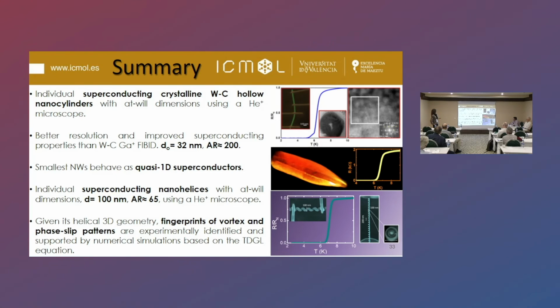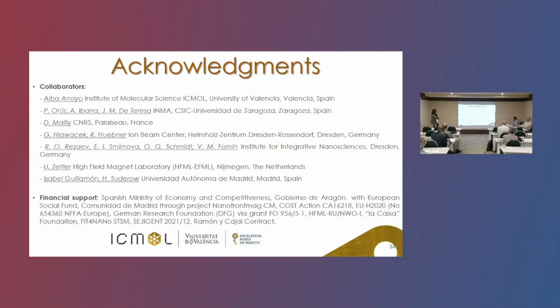The summary of this second part of my talk is that we were able to grow individual superconducting hollow nanocylinders and nanohelices with really small diameter and high aspect ratio. And this helical 3D geometry gives us fingerprints of vortex and phase slip patterns, experimentally identified and supported by numerical simulations based on the time-dependent Ginzburg-Landau equation.